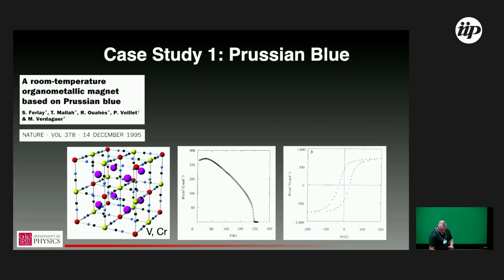Without further preamble, I'm going to talk about 2 case studies, not evenly weighted, much more on the second than the first. This first category of materials, the Prussian blue analogs, is, I think, arguably the oldest molecular-based magnetic system. The lattice structure here is meant to be somewhat generic. There are sometimes, but not always, the purple intercalent atoms, and the red and the yellow are 2 different metal species. In the case of this report, vanadium and chromium. It's nominally molecular based. You have some carbons and some nitrogens in there, and you can make these by chemical synthesis.